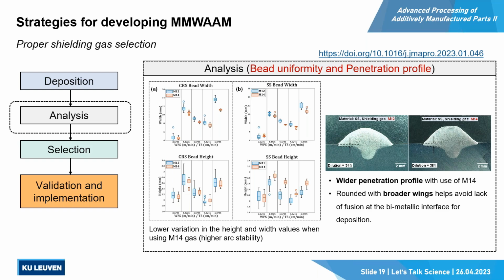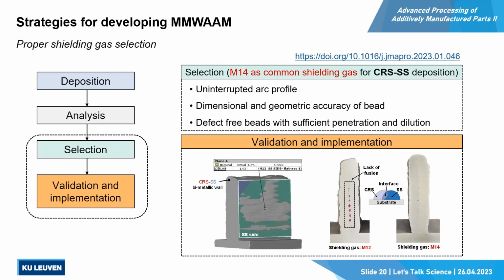In the next slide, I will explain about the deposition strategy. Yeah, to add one more thing, this result has been validated on a multi-layer component, which are the bimetallic walls. As you can see, using a proper gas, we could have defect-free walls, but the other gas resulted in a lack of fusion in the interface, which is not acceptable in additive manufacturing. And also it has decreased the flatness of the wall, which means lower machining allowance, and that's how we can save material in the multi-material deposition.